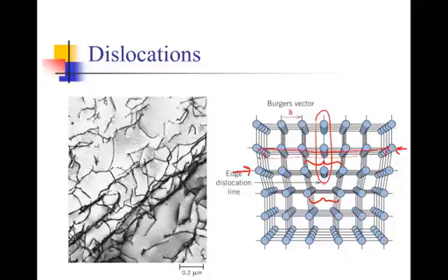So a two-dimensional area. However, if we have this dislocation in place, and we try to shift over the atoms that are between those planes with the dislocation, then because of that, this line of atoms can shift over and bond with this line of atoms. So it can shift over and become next to it, and then that will leave this line of atoms as being the one that's extra and doesn't have a line below it bonded to it. So we shift them over one row at a time, and it takes a lot less force to cause that to happen.